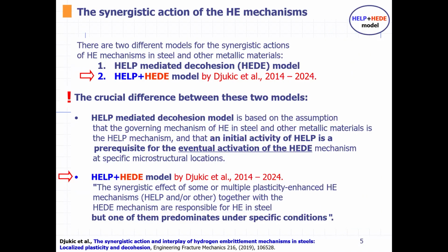So we have two models for the synergy, and here is the difference. The HELP plus HEDE model proposed in 2014 and 15 pointed out that multiple plasticity-enhanced hydrogen embrittlement mechanisms, HELP but also others, there are various mechanisms, together with the decohesion mechanism, are responsible for hydrogen embrittlement in steel. And recently it is confirmed that this model is applicable to almost all metallic materials.